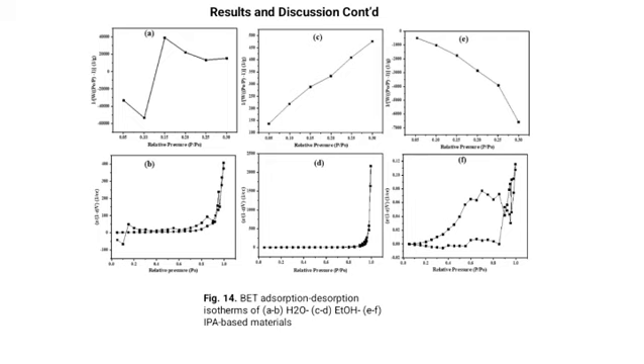The specific surface area obtained for the materials was 1.109, 2.486, and 0.017 meters squared per gram, and the pore volumes were 0.006, 0.015, and 0.0016 per gram for the water, ethanol, and isopropyl alcohol-based heterostructures, respectively. These results suggest bulk materials whose porosity may be altered by the co-solvent possessing different hydrogen bond strength